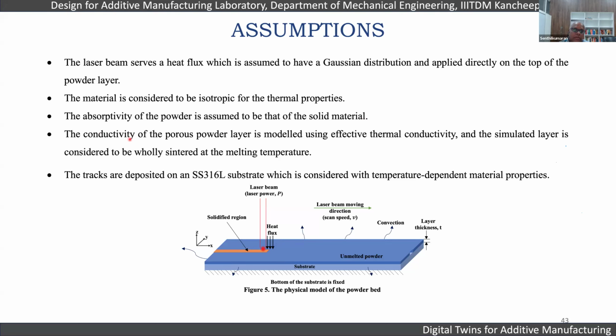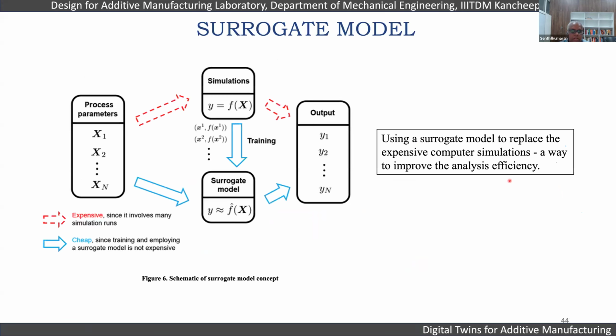We also modeled the conductivity of the porous powder as an effective thermal conductivity, taking into account the powder particles. We considered the conductivity of the air plus the conductivity of the powder, and since we know the volume fraction, the packing factor of that powder bed, we used the effective thermal conductivity as a material property. And then we have used an SS316L substrate, for which temperature-dependent material properties are being used.